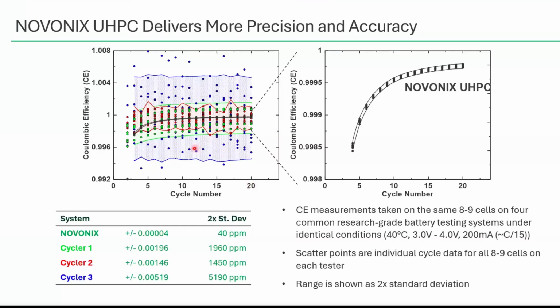This test is slow cycling at about C/15. You can see the spread in these identical cells on each of these different types of cyclers - this is actually showing up in green here, it's supposed to be black, I apologize. These 8 or 9 cells all have almost the exact same coulombic efficiency measured on the NOVONIX system, whereas everything else is 1 or 2 orders of magnitude larger in uncertainty.